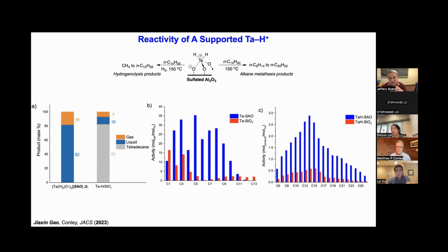the other polyolefin classes. Yeah, you're absolutely right. And that's a good point. That's something that I should probably put a little more pressure on Jiaoxin to try, because you would expect that you would get more branched products in those cases just because there's more branches. Yeah, if you can isolate highly branched structures, those are really valuable fuel additives, right? So like triptane, for example, is a good jet fuel additive. And that'd be pretty cool if you could convert low density polyethylene into jet fuel additive. That would definitely be an upcycling of polyolefins, in my opinion.